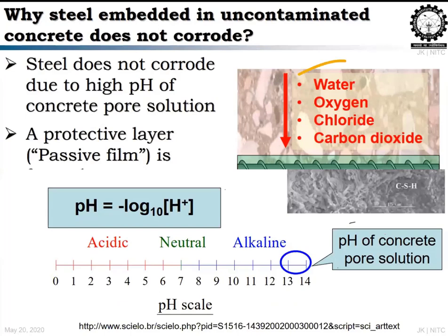Because of the chloride penetration and also carbon dioxide, which will collapse your concrete structure and create a lot of carbonic acid, which reduces the pH. So these are the major parameters which will initiate corrosion. What are the other major corrosion mechanisms that can lead to the initiation of corrosion? Freeze-thaw, alkali silica, delayed ettringite formation, sulfate attack, and many more we have in the list.